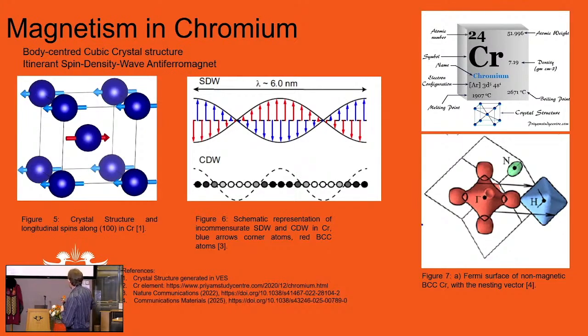Now, in the magnetic state, what happens then? Two things in parallel with chrome. One, you have the shift in the Fermi surface of these two surfaces moving to get nesting. The other is, remember, I have unpaired electrons already in the paramagnetic state, the random state above, where there's no magnetism, supposedly, if we sum over the metal. What then happens, all these spins are random. As you cool them down, you take energy away. The spins start to align.